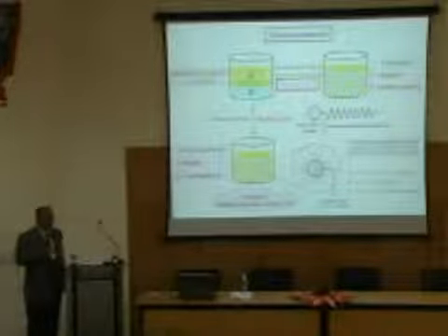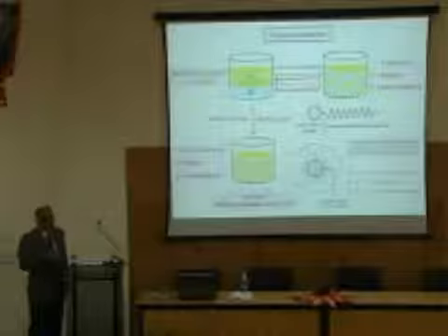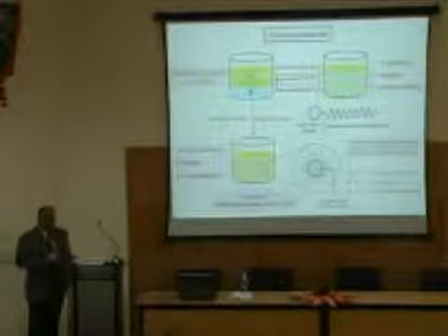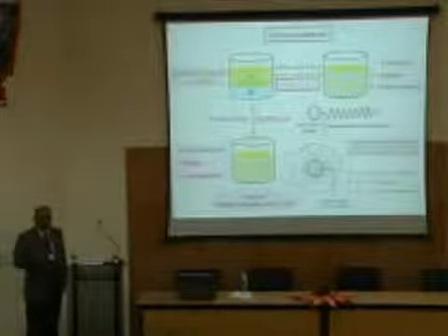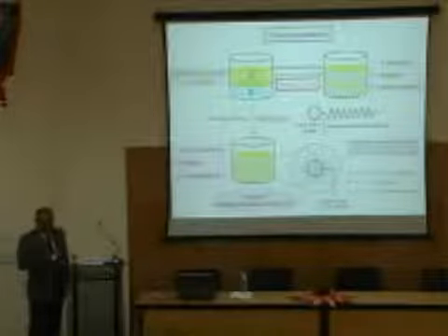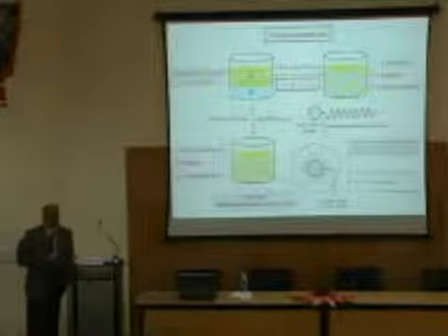After that, if you do reactions, then the molecules or particles which will form will take the shape of the template which you have generated in solution. Okay? So microemulsions basically give you a template to prepare particles of designated shape and of size if you can control the size. The size of this normally is in the nanometer dimension, and hence you get nanoparticles.